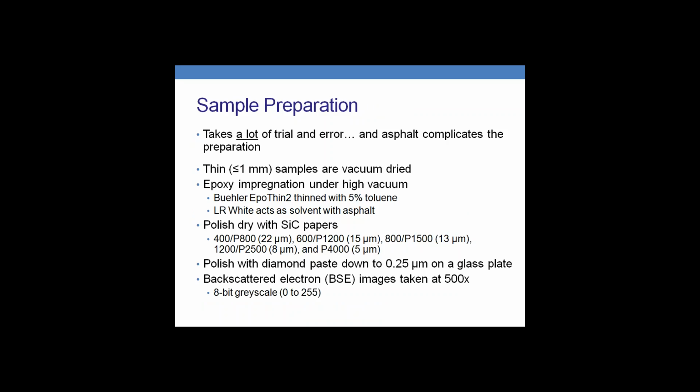Now, sample preparation is the biggest headache you will ever have to face. If anyone ever wants to get into this, once you figure it out, it's easy, but it takes many, many months of trying to get it to work. What you basically have to do is cut a thin sample, somehow get the epoxy to penetrate through your entire sample, and then polish it all the way down to sub-micron fineness. We needed that fine a polish to get good compositional contrast in a plane.